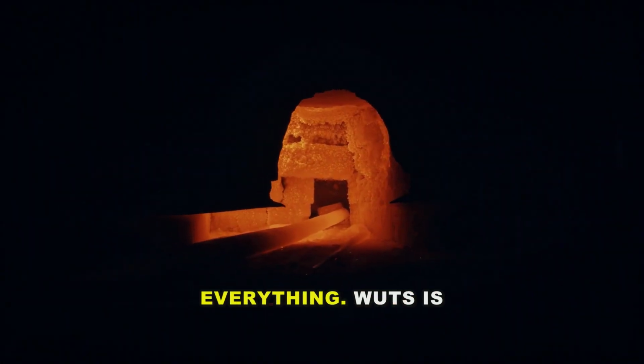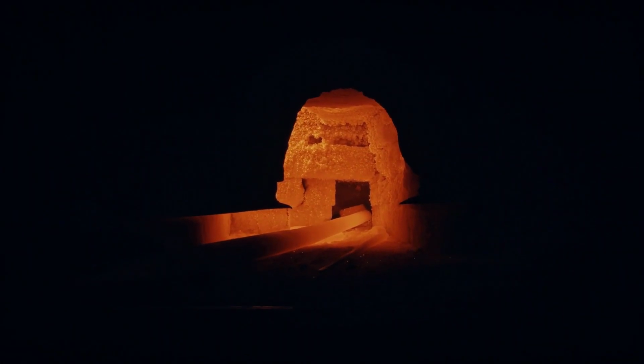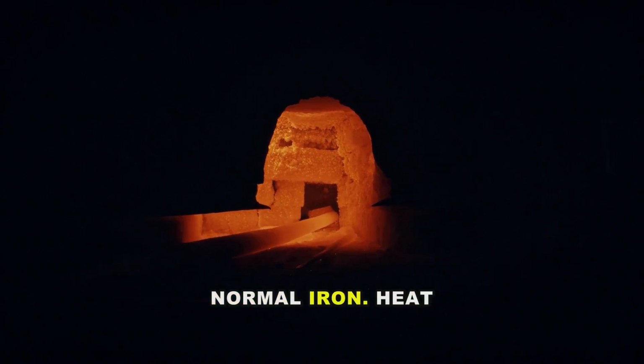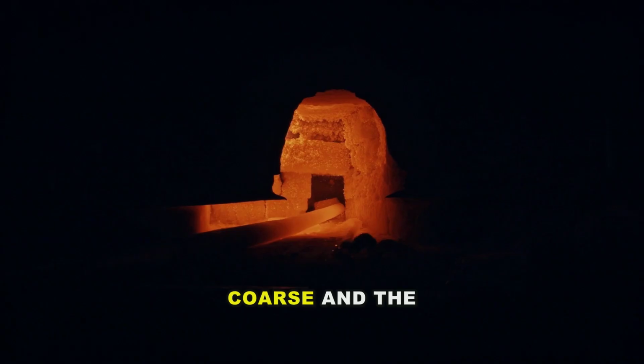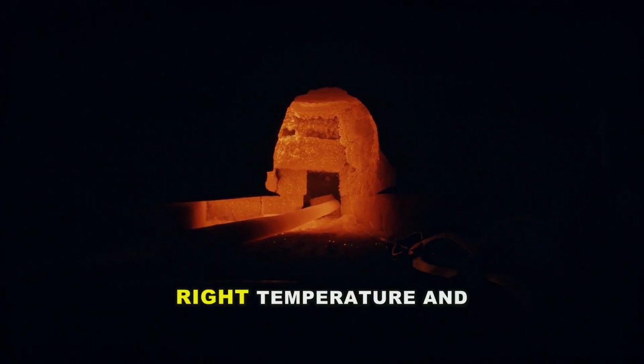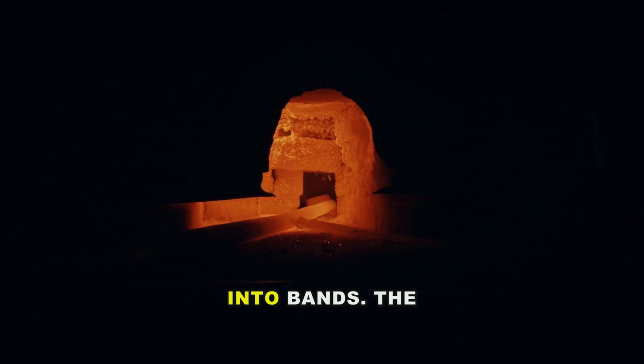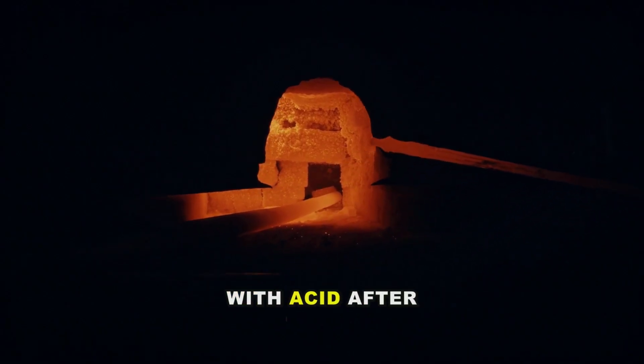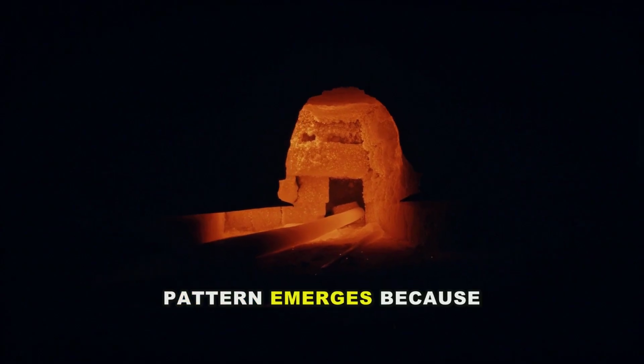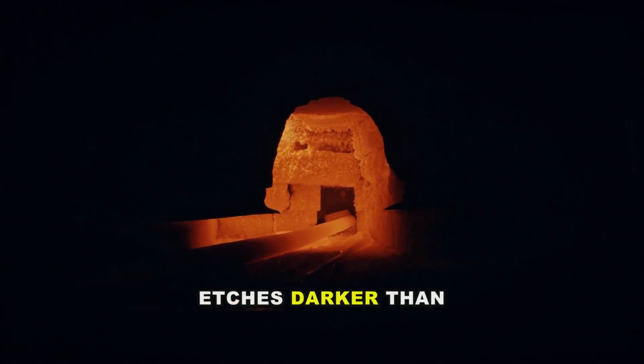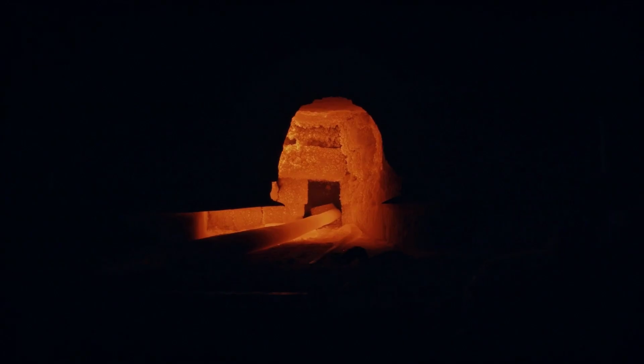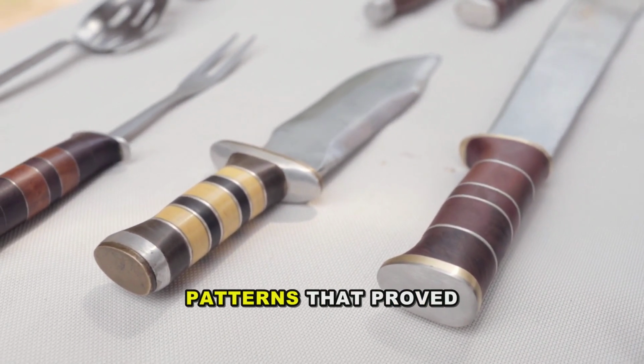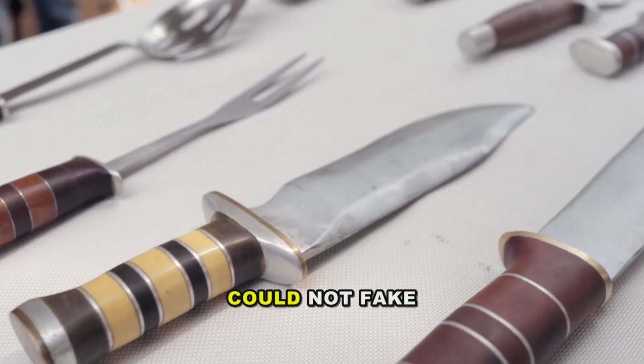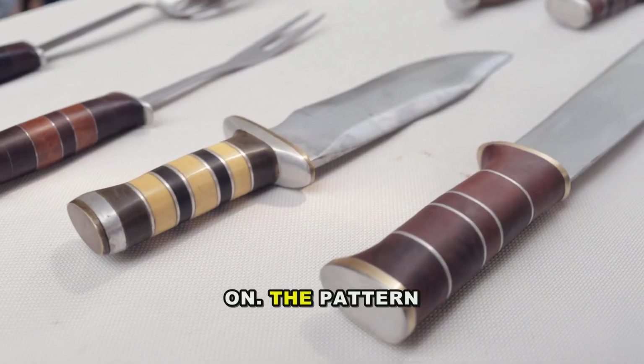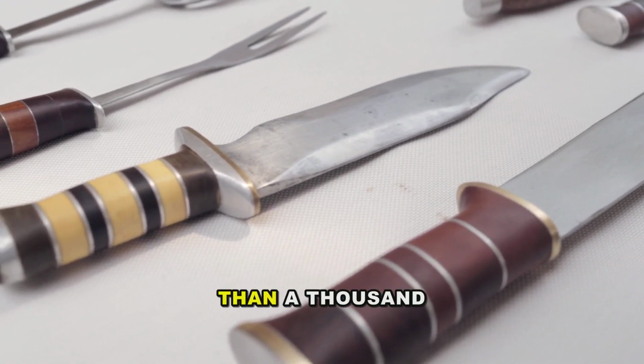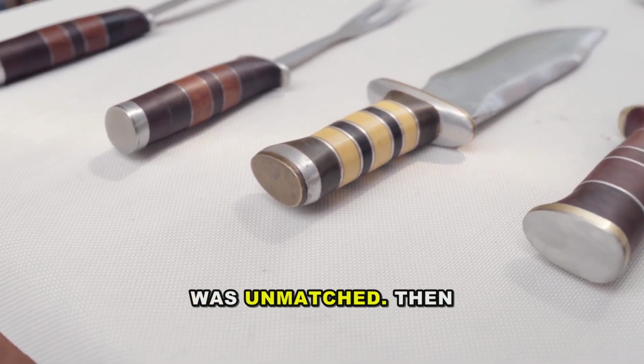The forging was everything. Wootz is hyper-eutectoid steel, too much carbon to behave like normal iron. Heat it wrong, and the carbides grow coarse and the blade cracks. Forge it at the right temperature, and those carbides align into bands. The surface gets etched with acid after polishing, and the pattern emerges, because the soft iron etches darker than the hard carbide lines. The result was a blade covered in flowing patterns that proved its ancestry. You could not fake it. You could not paint it on. The pattern was the steel, and for more than 1,000 years, that steel was unmatched.